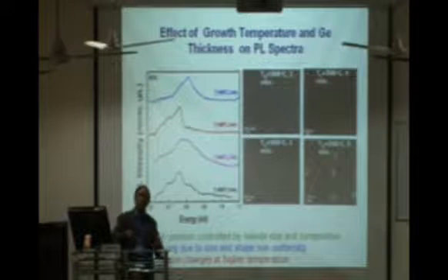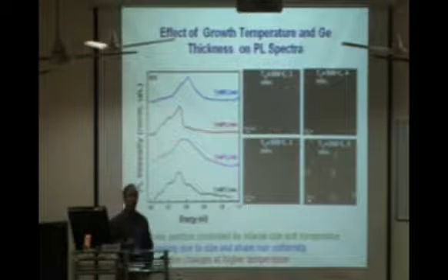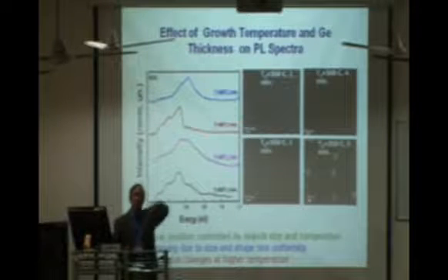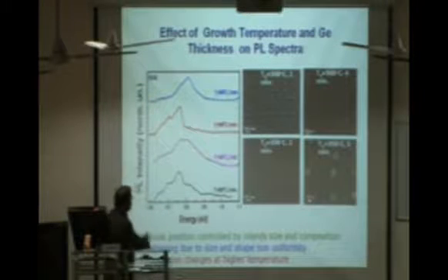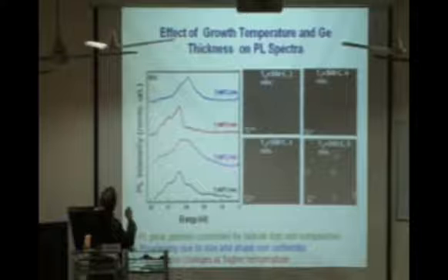Because of the formation of excitons, ultimately the excitons decay and recombine and give what is called photoluminescence. In fact, what we do is excite these quantum dots with lasers, and finally you see their recombination mechanism by an experiment called photoluminescence. This photoluminescence experiment is done for these germanium quantum dots. Normally it is taken at a low temperature like 10 Kelvin, and we can get very good emission.